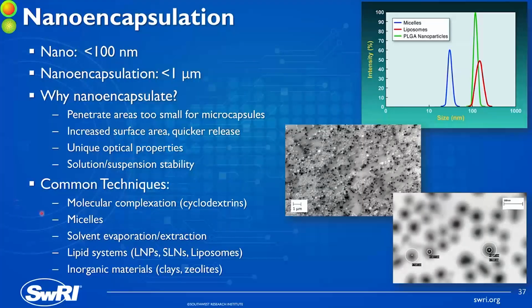Some of the common techniques that fall more into the nanoencapsulation realm: molecular complexation, something off the shelf like a cyclodextrin. So you're complexing a lipophilic molecule with the inner structure of a cyclodextrin molecule. It's not a core shell morphology per se, but you are loosely encapsulating it. Micelles as well. You're making an emulsion with a surfactant. You can cross-link some of those surfactants to make a very thin shell. It may not be mechanically robust, but it can help prevent some coalescence.